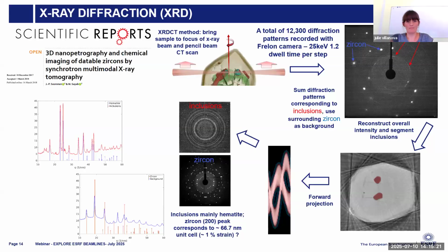The example that I want to show you today about diffraction is a geological study. The samples were grains of zircon in which there are some inclusions. The idea was to understand what those inclusions are and also where they are situated. The experiment was performed in 3D, meaning that we have the grain of zircon, we scan along the grain, and at each point we record one 2D diffraction pattern, and then you turn, you scan the line again, you turn, you scan the line again, and so on. So at the end, you have more than 12,000 diffraction patterns.